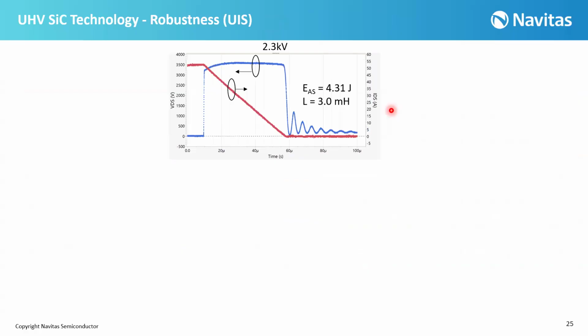Here's the UIS robustness for 2.3 kilovolts. The VDS reached around 3.5 kilovolts before the failure, and the peak current before the failure is around 52 amps. The avalanche energy is 4.31 joule.